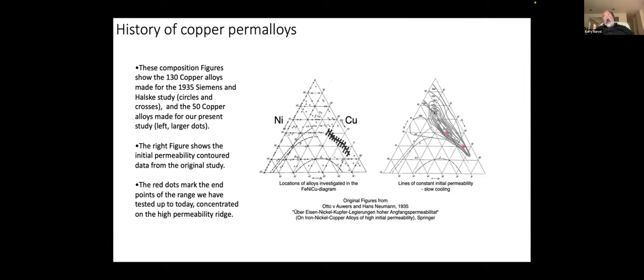There's also a line that goes down here through the middle, which is a zero magnetostriction line, which also plays into the high permeability, low anisotropy properties. But on the high iron side over here, you can see it bleeds into this segregation area pretty quickly. And on the other side, it falls off pretty quickly too. So the interesting zone was pretty narrow, and we've actually chosen a set of alloys with about a 5% spread.